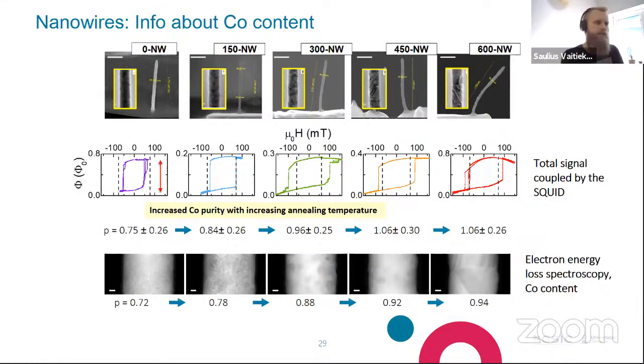I see. And now, the second question was? The second question is about whether you can resolve it spatially to some extent at least, let's say along the wire, if there is a domain wall and a flip of the magnetization along the wire, if you could tell the location of that. Right now, this is very difficult because what we measure is the convolution of the signal of the whole sample. Ideally, what one would need to do is to be able to move your sample, or to move your sensor, like in microscopy. For instance, the group in Tübingen is developing a SQUID microscope based on YBCO, and from my side, I am trying to develop techniques that allow me to move the magnetic sample in situ through the device. I'm working on that also.